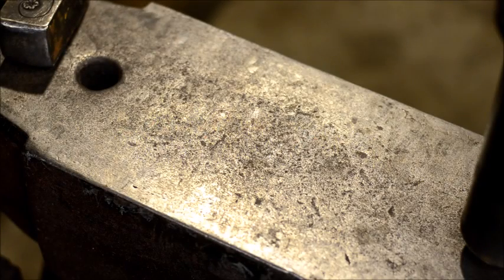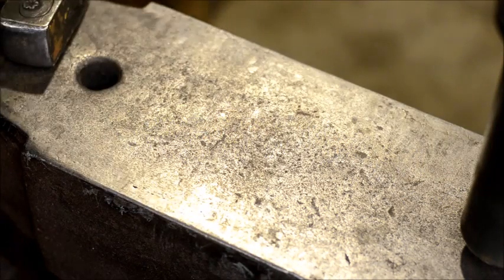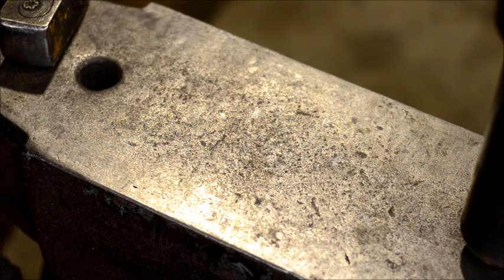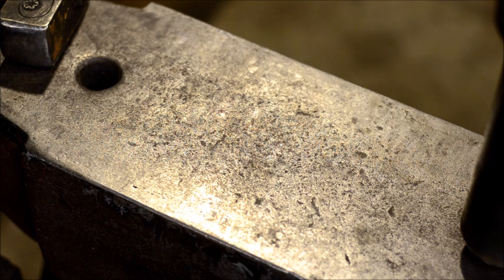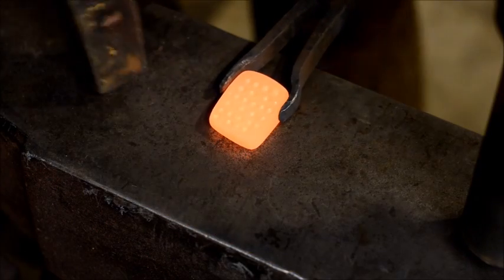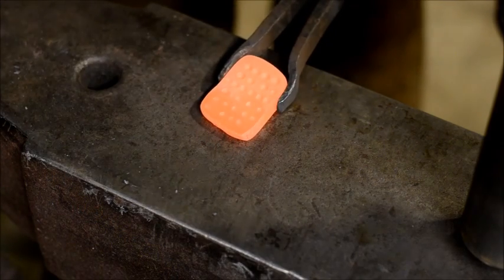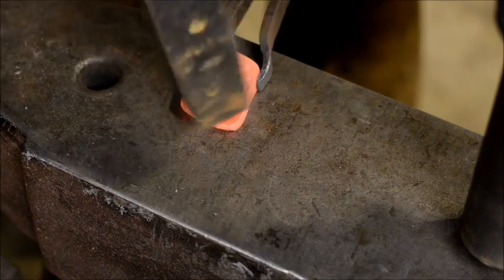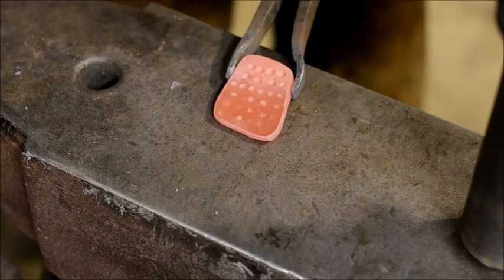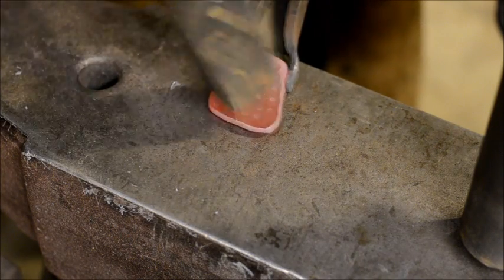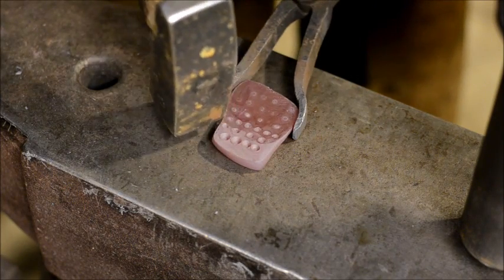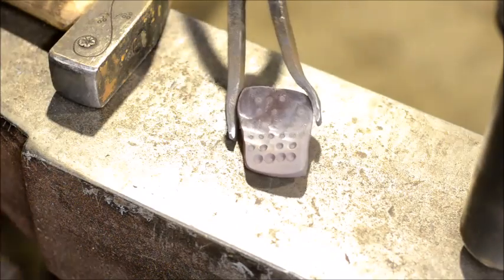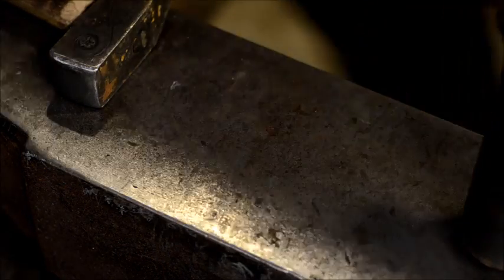Okay ladies and gents, I've got my material almost up to temperature. It's important to note you don't want to work this at a large weld heat anymore. You want to bring it up. The piece is already welded together very well. We just want to bring it up to a nice bright red or orangish color and forge it out from there. We're just going to hammer this out and try to compress those round dots down a little bit without making cold shuts. So we're just coming straight down and flat on those dots. We do not want to try to move material together. That's what we don't want. As you can see those compress flat there on the other end and you can kind of see a residue of those. So we'll take another heat on this.